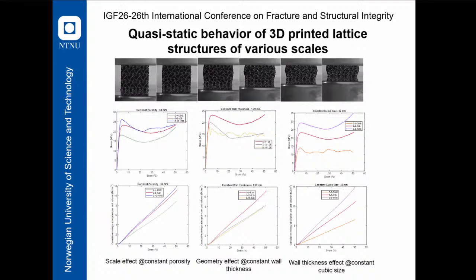So the title of this presentation is Quasi-Static Behavior of 3D Printed Lattice Structure of Various Scales. In this work, we use PLA printed lattice for different scales, and it's all uniform lattice, which means the unit cell is constant instead of gradient, and we had three categories. So we studied the scale effect, which is under constant porosity for the lattice. This is the first case. And we also studied the geometry effect, which we had the constant wall thickness for each lattice. And also we studied the wall thickness effect, and in that case the lattice would be constant unit size and cubic size.